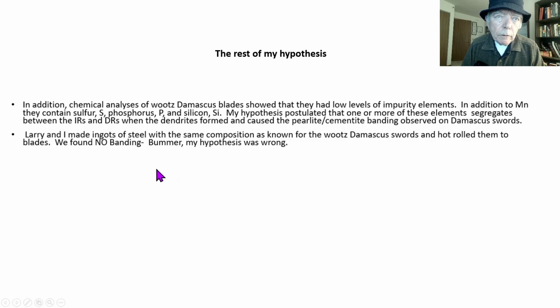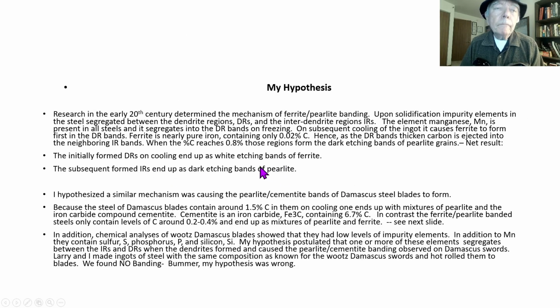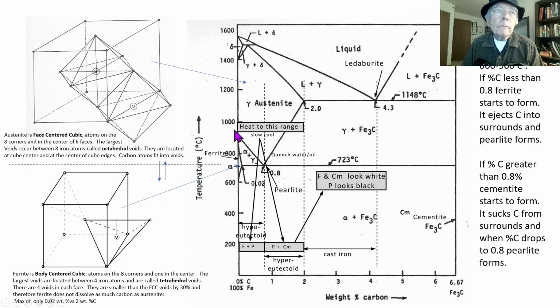So, knowing this, which is quite fascinating, I made the obvious hypothesis. Because the steel of Damascus blades contains 1.5% carbon in them, on cooling, one ends up with a mixture of pearlite and the iron carbide compound cementite. The cementite is an iron carbide, Fe3C, 6.7% carbon. In contrast, the ferrite pearlite banded steels only contain low levels of carbon, around 0.2 to 0.4. So they end up as a mixture of pearlite and ferrite. So here's what you got to understand.